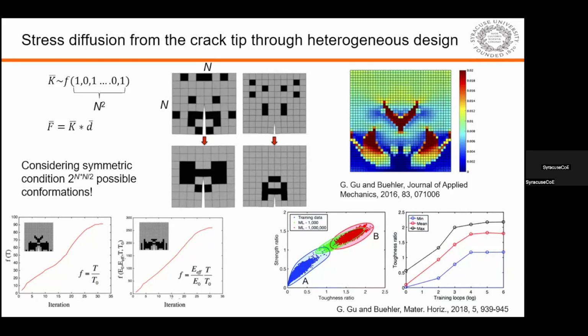Then the elastic matrix of the entire sample can be given as a function of the stiffness of each pixel. We can determine the loading force by using the finite element method to solve the constitutive law, and further get the stress and strain distribution. The reason to start with this small number of lattice, 8 by 8, is computational capability, because the more lattice you have, the more possibilities you get. With 10 by 10, you have 2 to the power of 50 possible conformations. But by using the greedy algorithm, we can still obtain a locally optimal geometry.